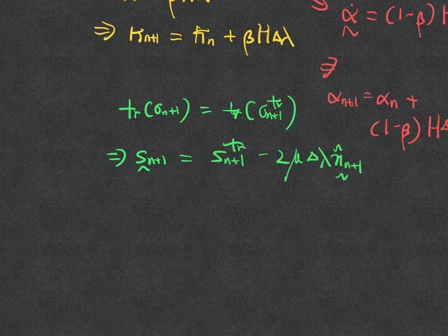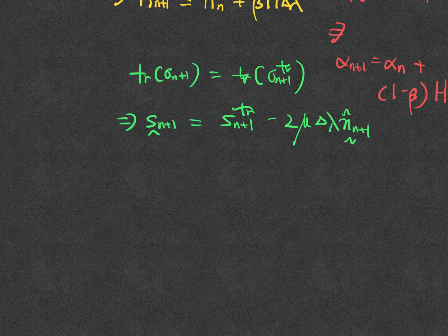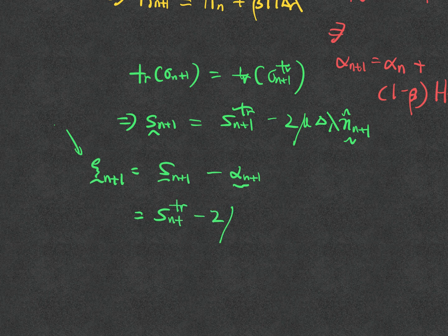Now go back to this. So we are in the deviatoric stress. What actually happens is that I also need to consider the difference between the deviatoric stress and the back stress. Can this thing become bigger or smaller? It could, right? Because I have a combined kinematic hardening, so the difference between them keeps evolving. So if I substitute what I have here, then I will have this term.